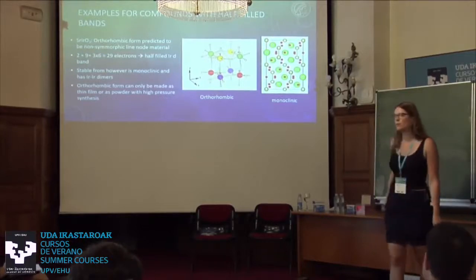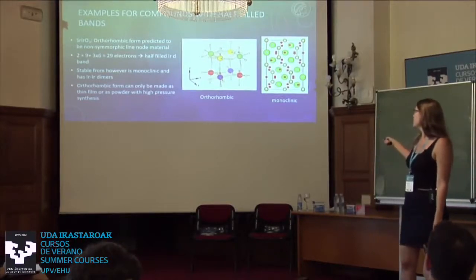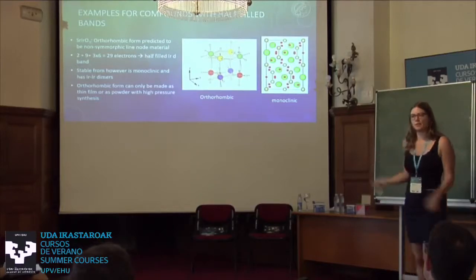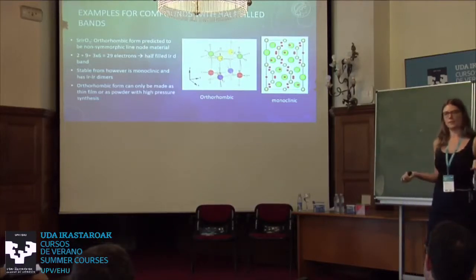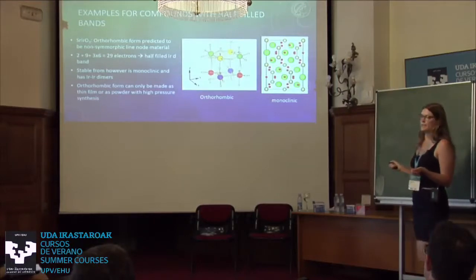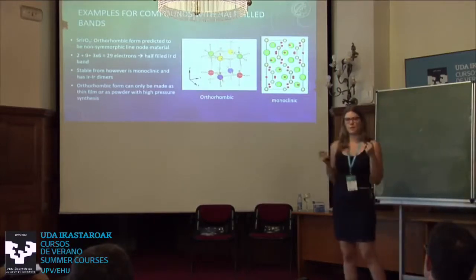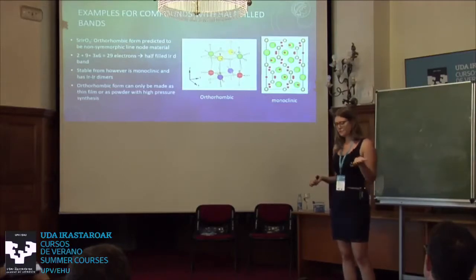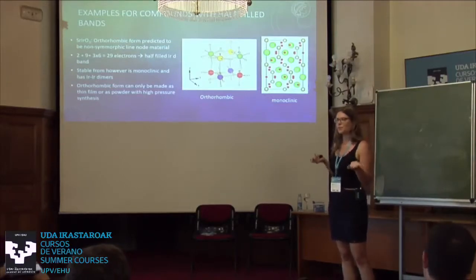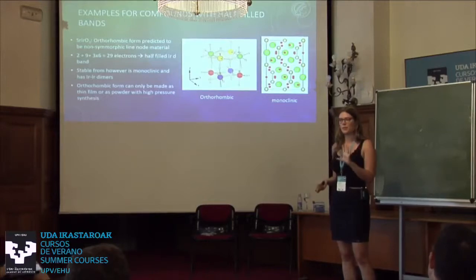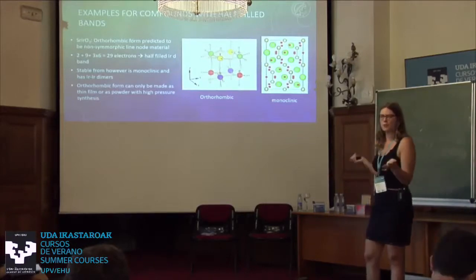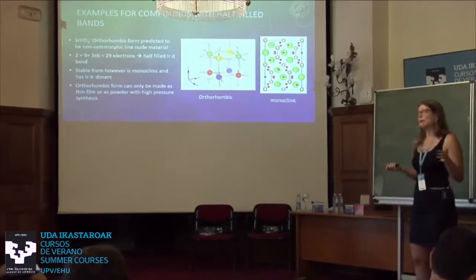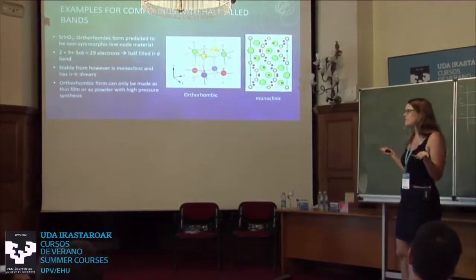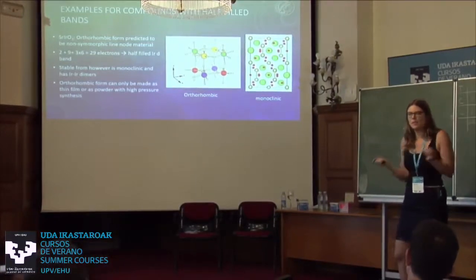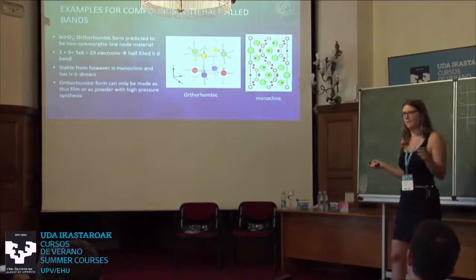So if you just make a normal synthesis, you will always get the monoclinic one, and the monoclinic one has iridium bonds, so this will be gapped again. So it's the same kind of Zintl concept. This phase, however, does exist. It is a high pressure phase, and it has been done. The problem is that you cannot be 100% sure with high pressure phases that the structure is solved completely correctly. The crystallinity is often not good. Not everything which is listed in the ICSD is correct. And so maybe this exists and it has a half-filled band, but maybe there's some really subtle distortion people have missed so far.